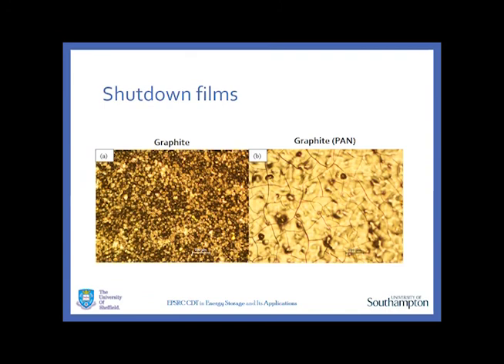And you can see on the right, which has been causing me quite a lot of hiccups in my work, the surface of the polymer is quite cracked. Ideally, I'd like a nice clean film where only the pores are allowing the ions to transport. The problem with the cracks is that if they're too large, they will allow the lithium ions to move through even when I hit these higher temperatures. But cracking is an inherent property that you tend to get when you electrograft the polyacrylonitrile because it will crack during the drying process of the electrolyte, which is something I've been trying to remove throughout my work because this cracking is not good for my potential operation at higher temperatures.